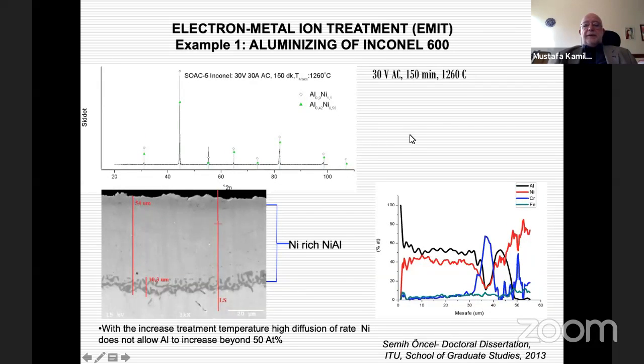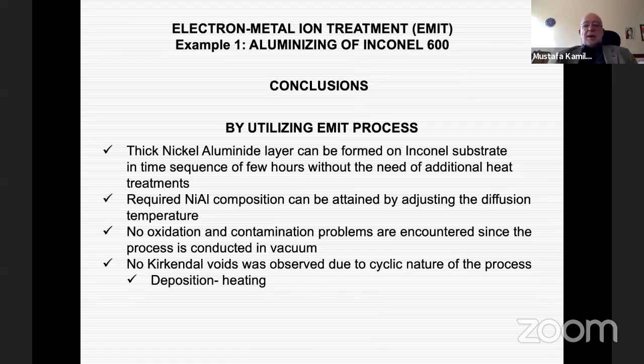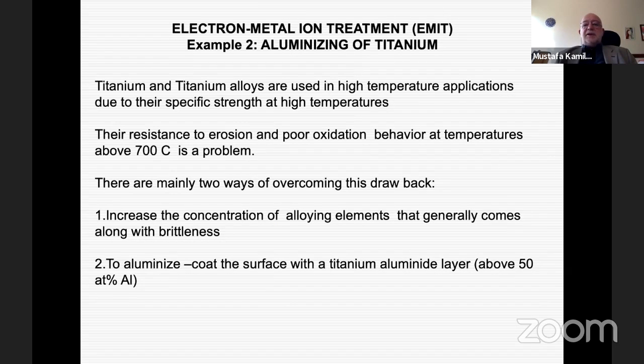And then when we further increase the temperature, in this case, the high diffusion rate of nickel does not allow aluminum content to increase above 50%, so we always stay in the high activity region, and we also have, in this case, nickel-rich nickel aluminide formation. So this shows us that there is a potential of this method for production of aluminide layers on nickel. So then we tried to also apply this method to titanium.